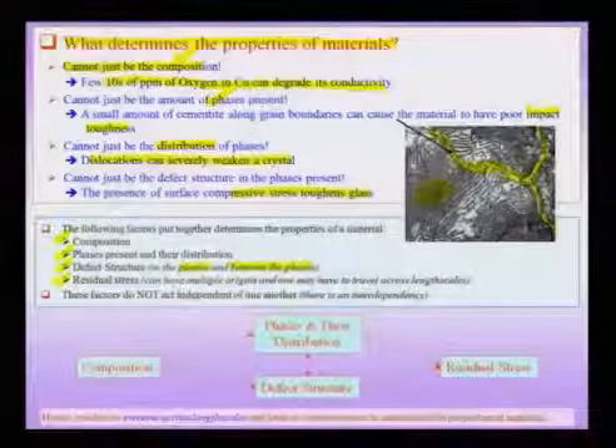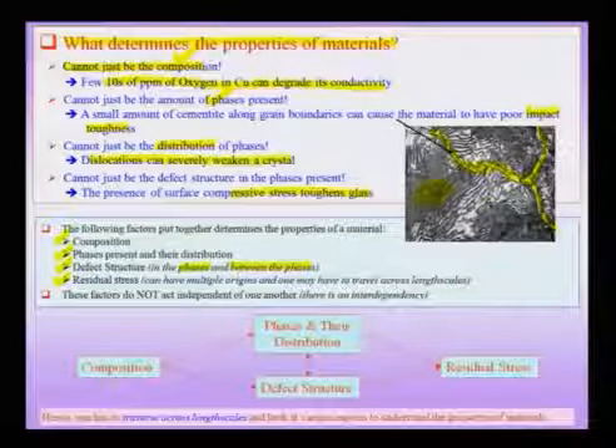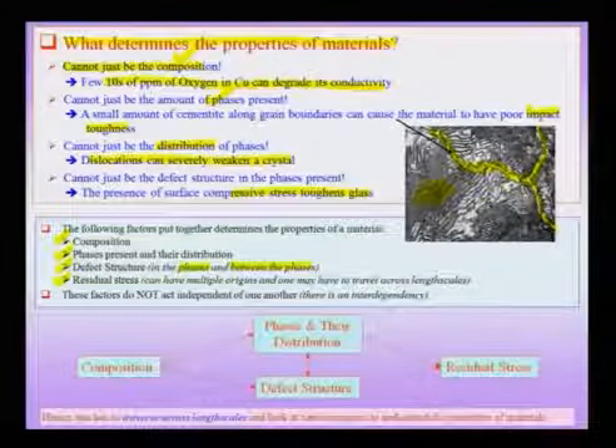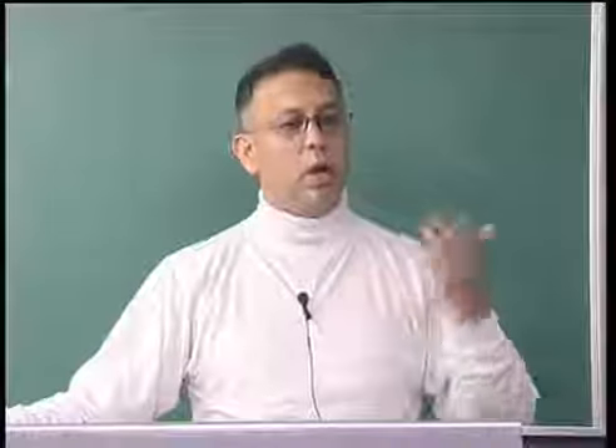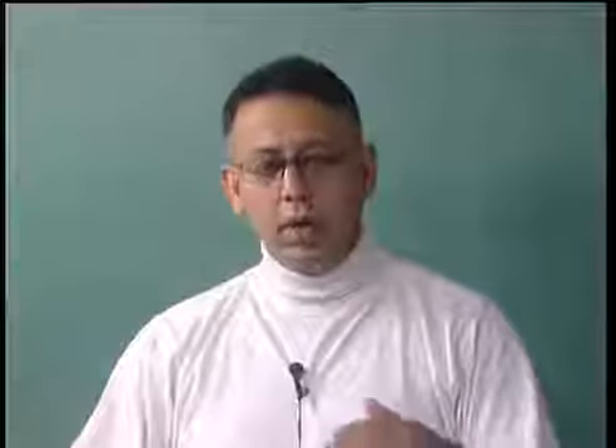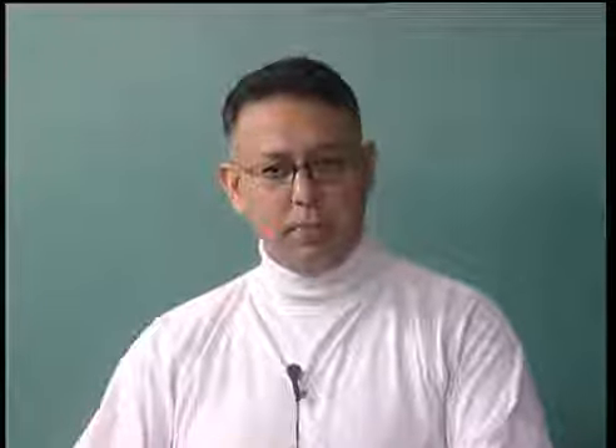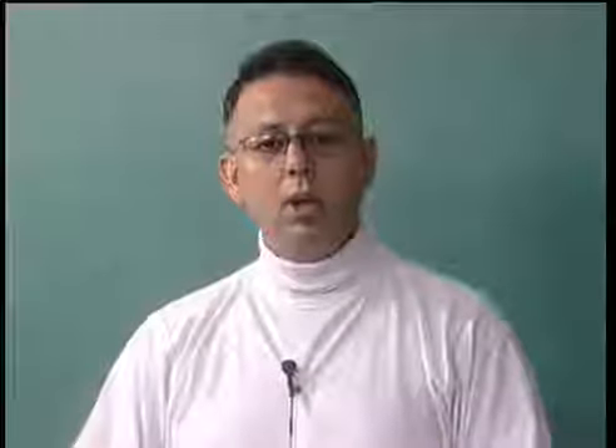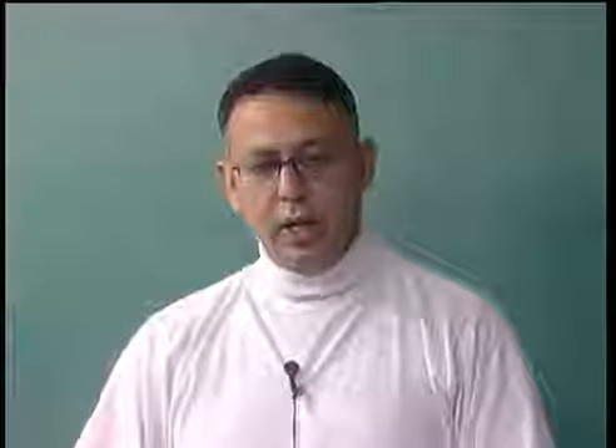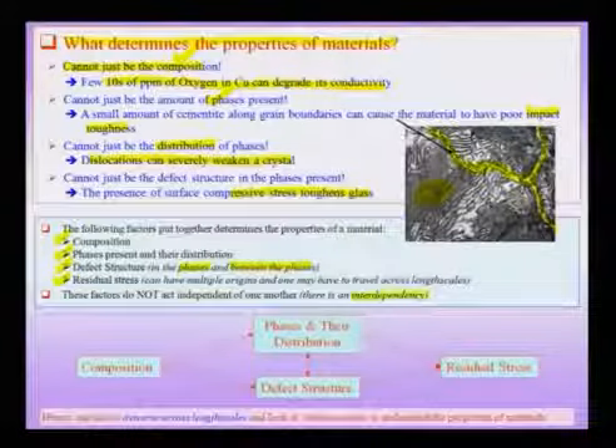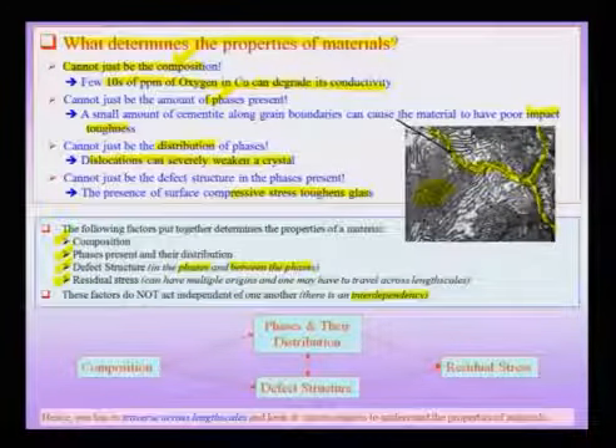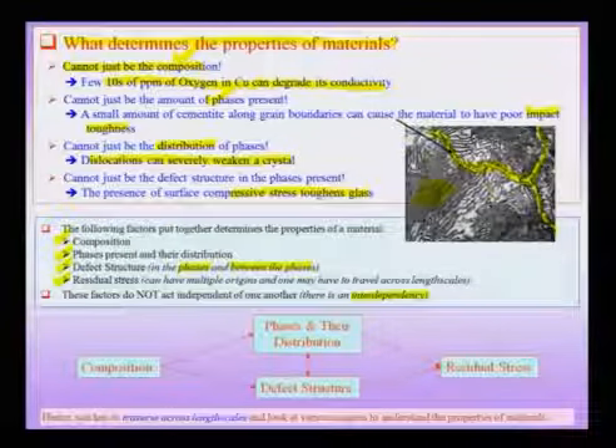And in doing so I would realize that these factors are not independent of one another. They often talk to each other, they talk to each other across length scales. To give an example, suppose you had a coherent precipitate. A coherent precipitate is not only a defect in the perfect single crystal in some sense, but also is associated with residual stresses. Therefore, the precipitate and the residual stress are intricately intermixed in the case of a coherent precipitate. Therefore, there is a lot of interdependency among these factors, and this interdependency often gives rise to the properties which one observes in a material.